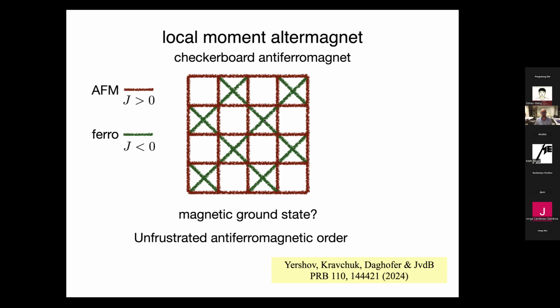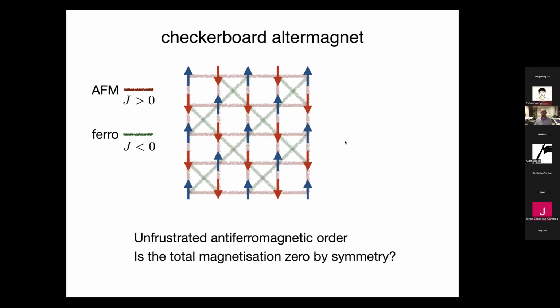And actually, the answer is really simple, because there is no frustration of antiferromagnetic order. These here in green, I have ferromagnetic bonds. So the two sublattice antiferromagnet will not be frustrated and will be the ground state of this model. So now, having an antiferromagnet, we could ask again, is the total magnetization zero? And just looking at this picture, you say, yeah, obviously the total magnetization of this magnet in this ground state is zero. I have as many up spins as I have down spins.